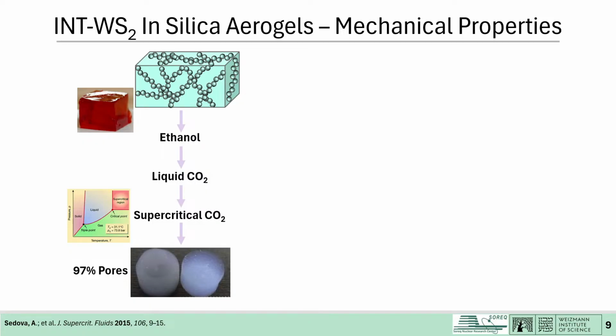So what we needed to do, we were working in ethanol. The gelation was in ethanol. Then we replaced the ethanol with liquid CO2. Then we needed to arrive at supercritical conditions, where we cannot distinguish between the properties of the liquid and the gas. And at this point, we could basically vent the supercritical fluid and obtain a dry product.